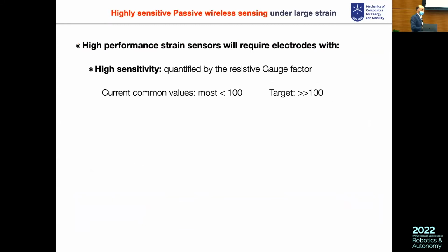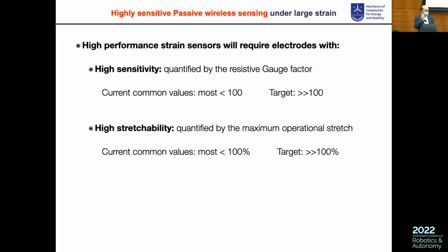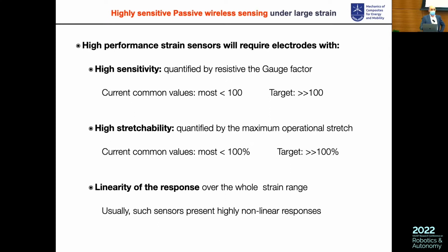So that means at the beginning, if you want to make it work, you want to have electrodes that will have a piezo-resistive gauge factor that is very high, let's say above 100, or at least between 50 and 100 compared to what is on the market. You want something that is very stretchable. You want to sustain around 50 to 100% of expansion. And then you want a relatively linear response, because if you want to invert your equations and understand your system, it's always good to have a relatively linear response.